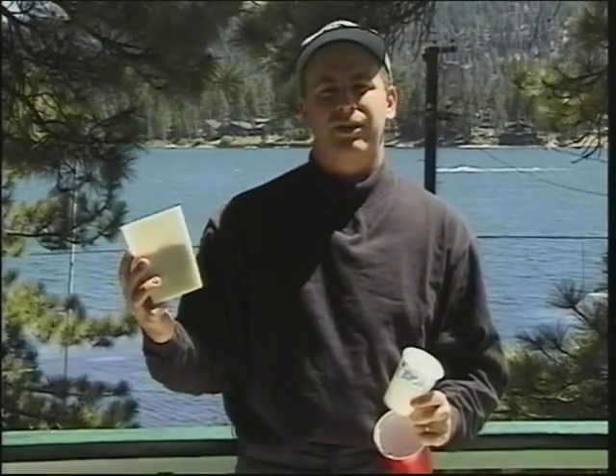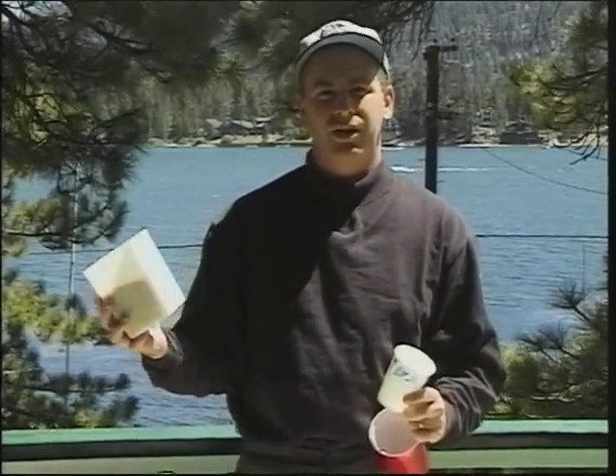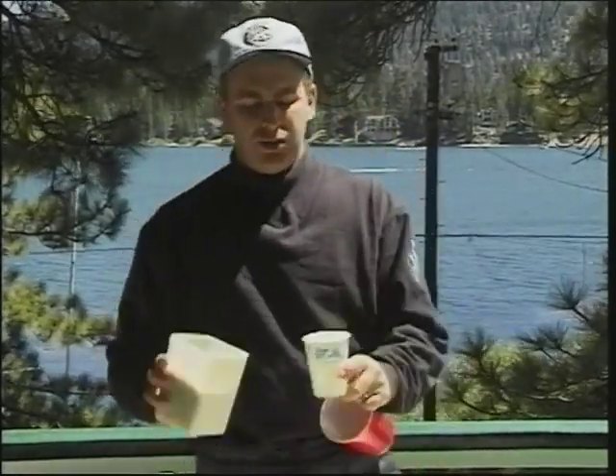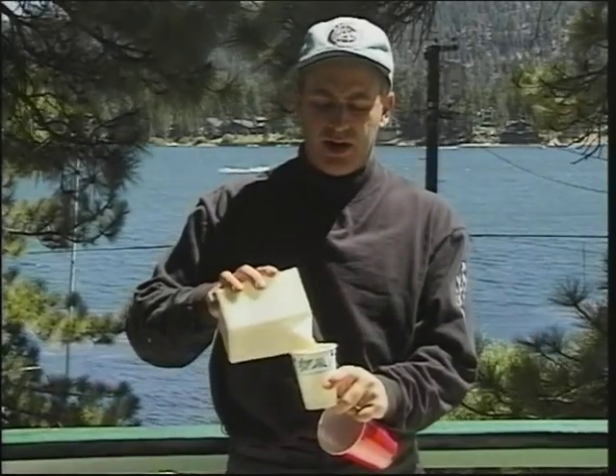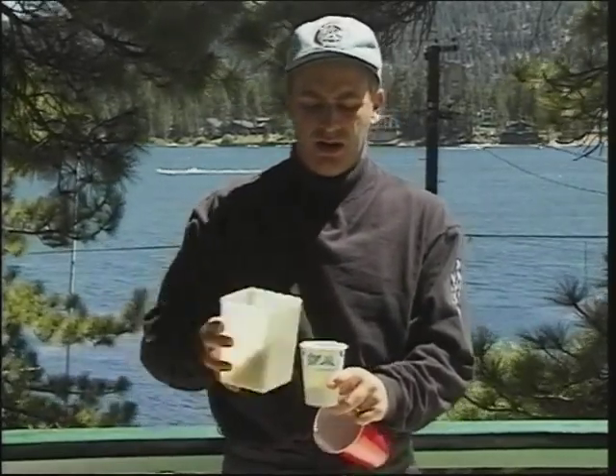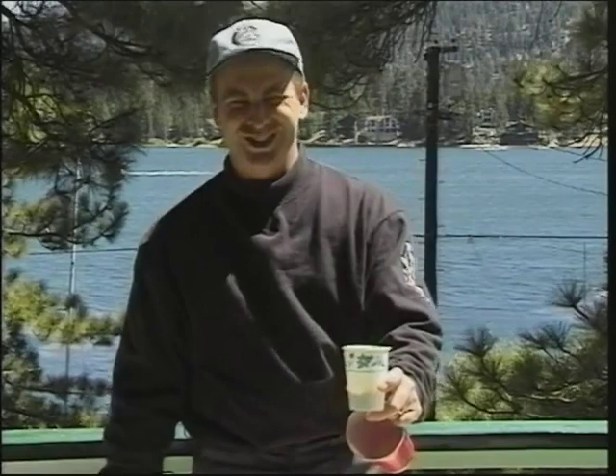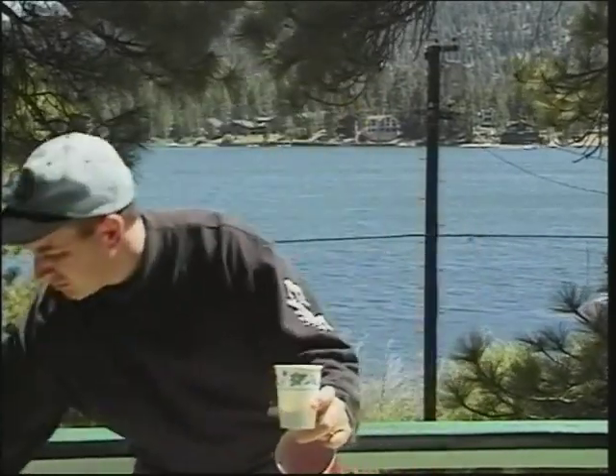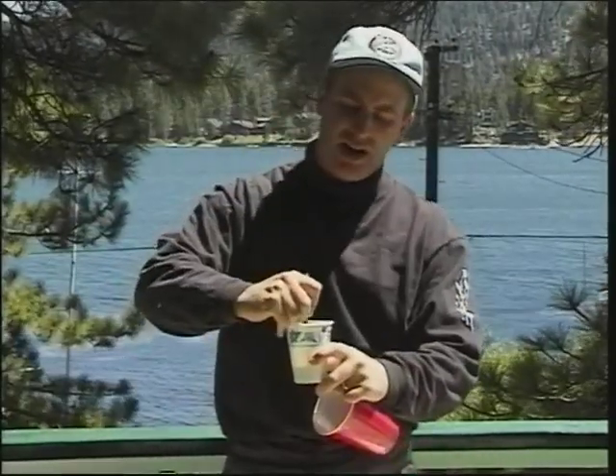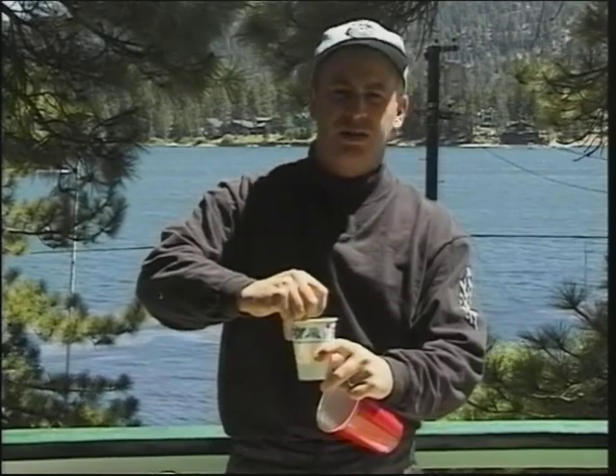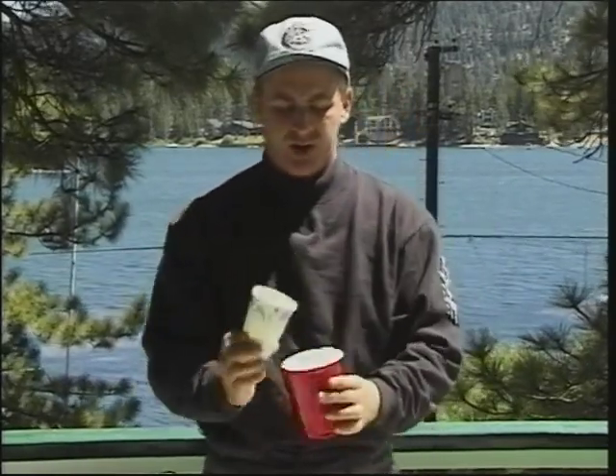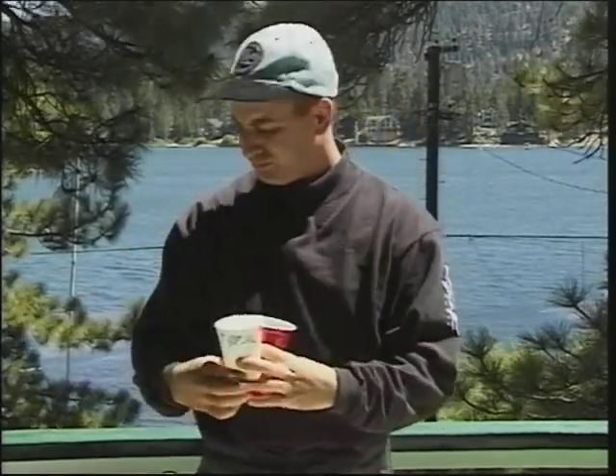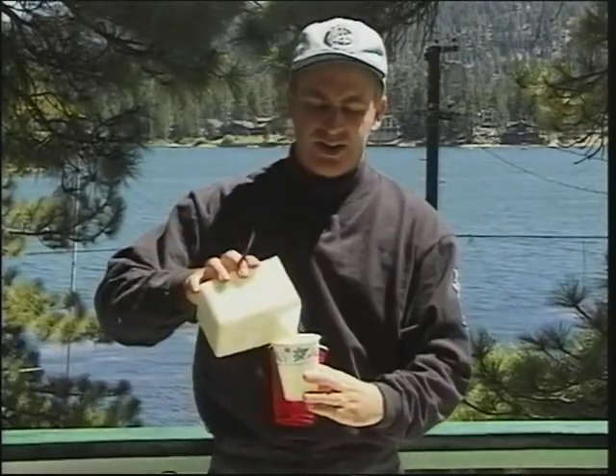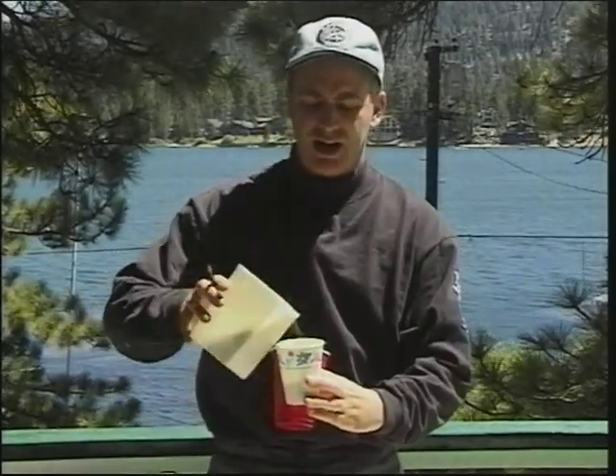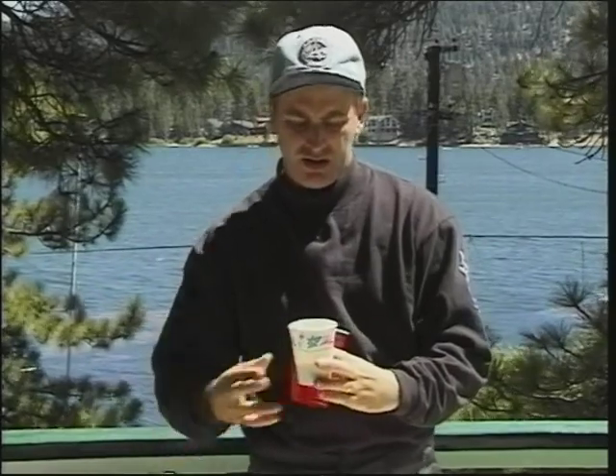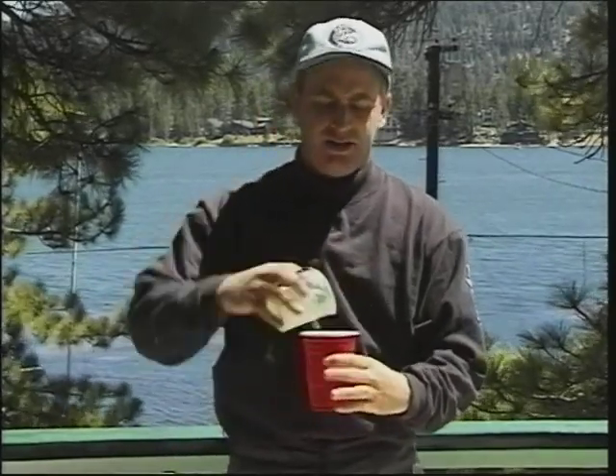Take some rice, just common household rice that's in a container, and into your small cup pour about 1/3 of the final amount of resin that you expect to use. When you've got that in there, make a mark on the inside of your small cup. Then pour it into the big cup. Add more rice to the small cup until it comes up to that level. Add it to the big cup.